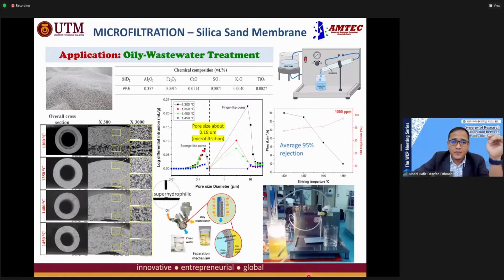The first material that I would like to emphasize is the membrane that we produce from silica sand. Silica sand is everywhere. We obtain silica sand that has a very high purity of silica, 99.5%. And by varying the sintering temperature, we can produce the membrane with a specific pore size, a narrow, precise size of 0.18 micron, which falls under microfiltration.